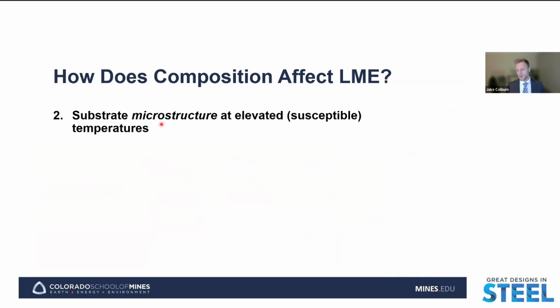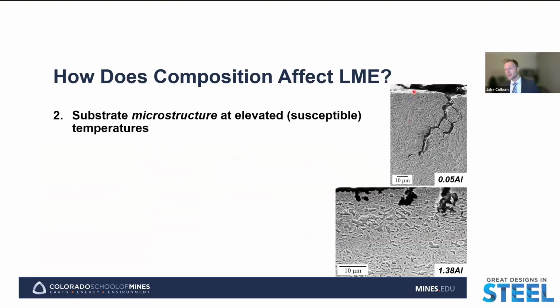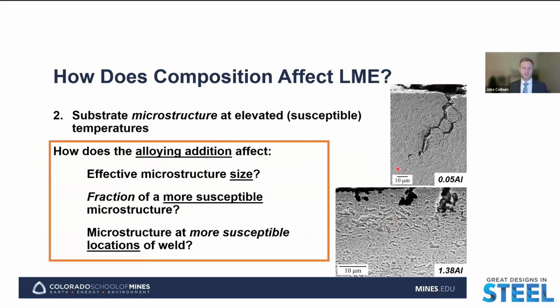And then if we go to the substrate microstructure, again, comparing this supercritical HAZ to an intercritical HAZ, the microstructure that is present there is going to affect the effective microstructure size. So here we're saying, how does that alloying addition affect the effective microstructure size? Again, are we potentially having single phase or 2-phase microstructure present at elevated temperatures? And then what is the fraction of those more susceptible phases potentially at elevated temperatures, as well as also the location of that?